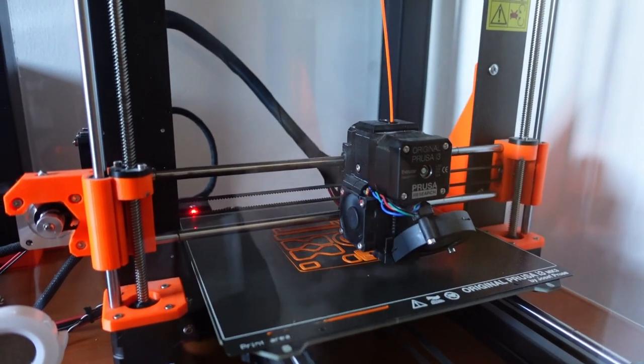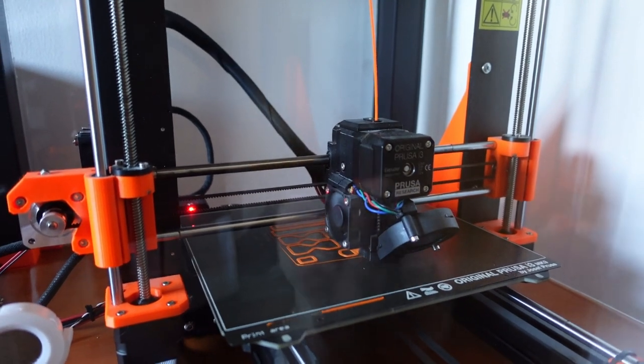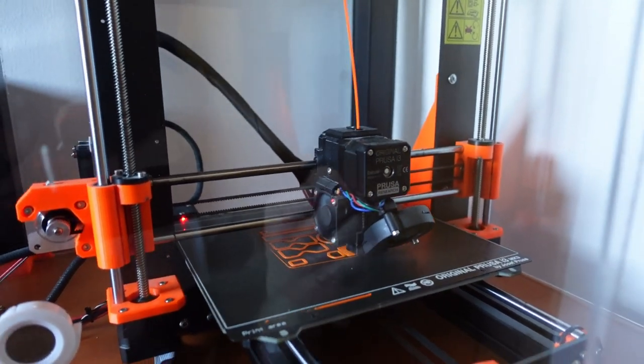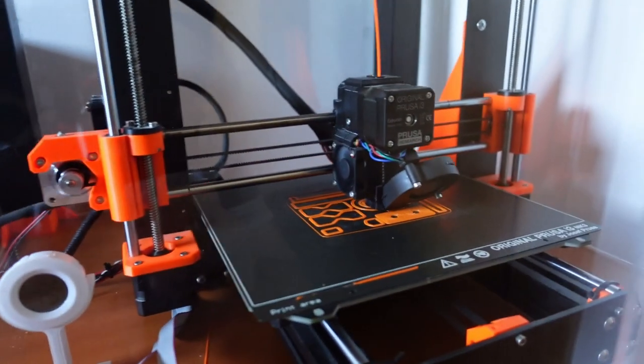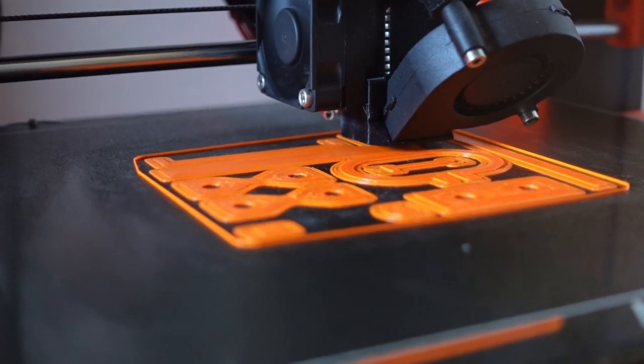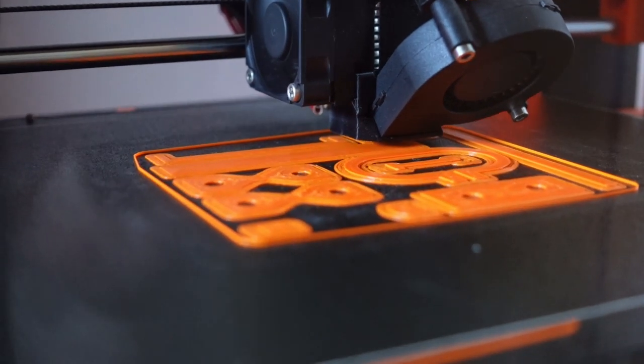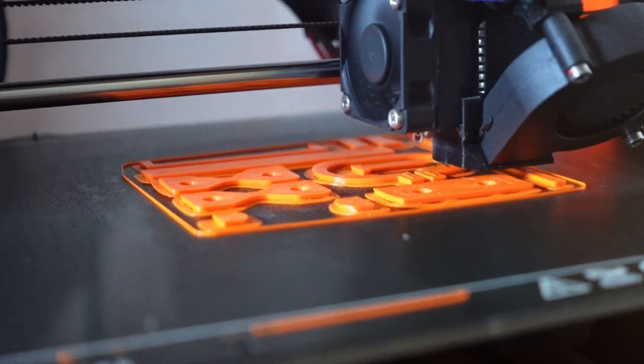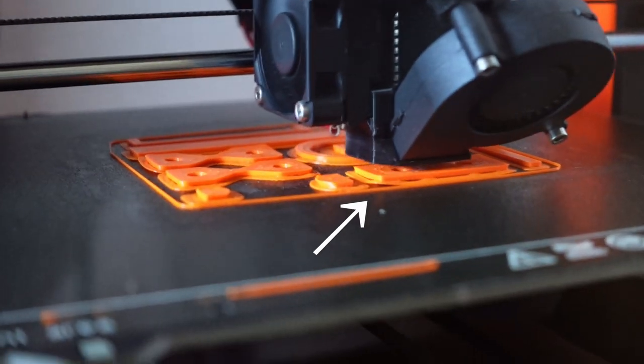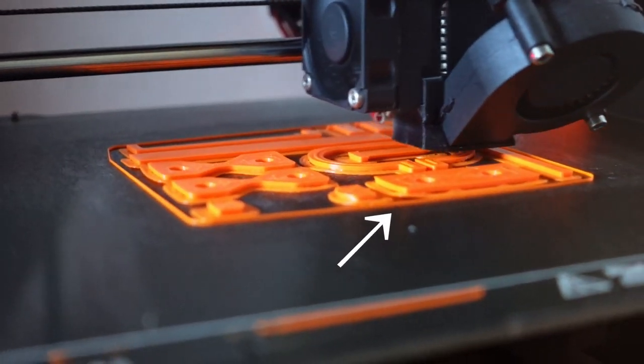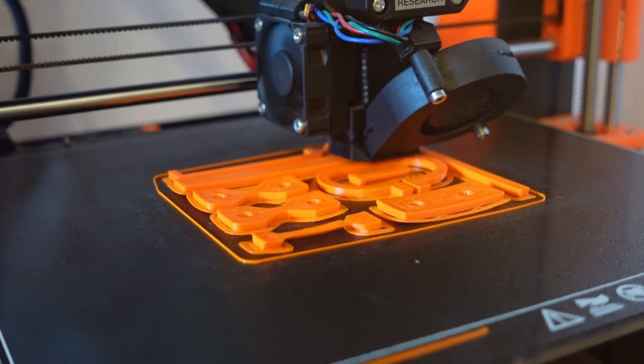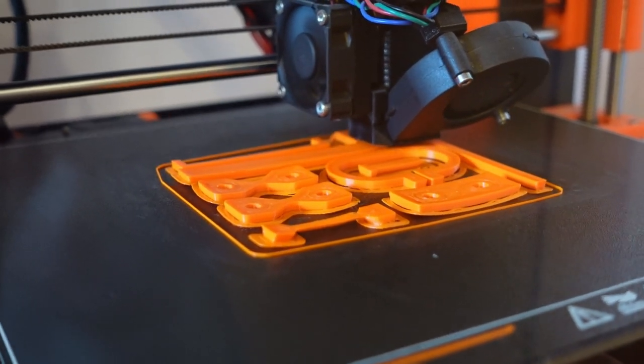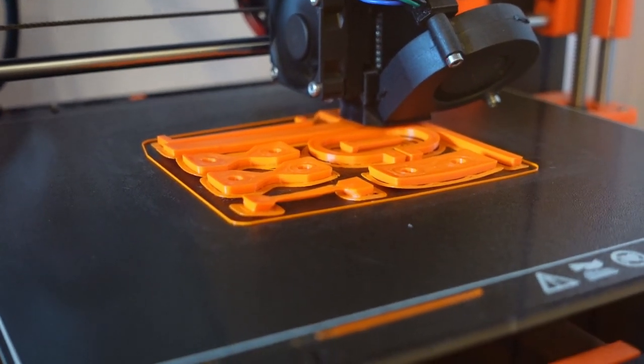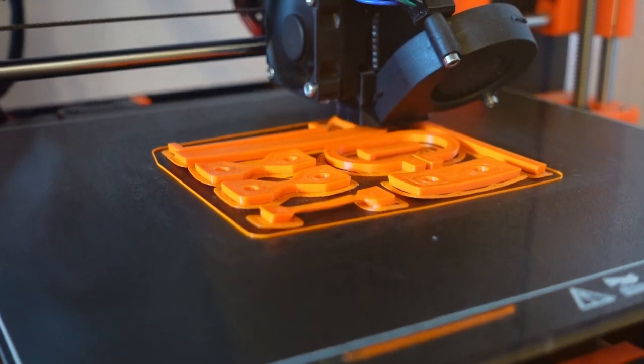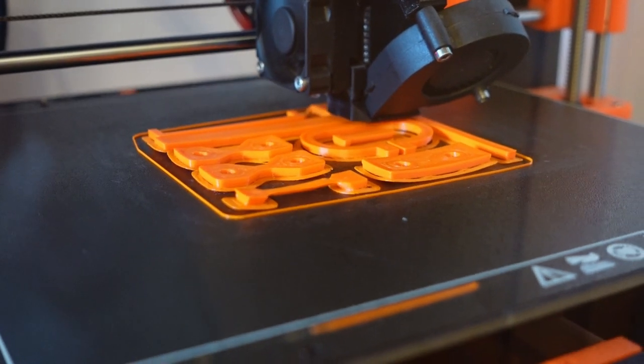So it starts with the brim and then it prints the objects, and already after maybe 15 minutes on the first layer, the temperature inside is 40 degrees Celsius. Perfectly straight, and I hope it will stay like that. After approximately 1 hour of printing, I can see small warping on one corner on this rectangle test object. Well, after 2 hours of printing, I can see that this will not be a successful print. I can see a warping on almost every object, so just a matter of time when will it fail.